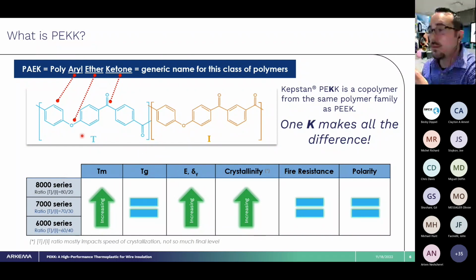The 8000 series would be an 80-20 of the T to I, with T being the higher percentage. The 7000 would be a 70-30 ratio, and the 6000 is a 60-40 ratio.